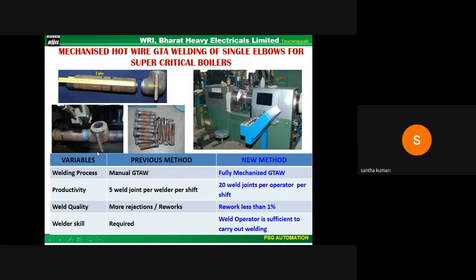Mostly, 5 weld joints used to be made per shift by a skilled welder. With the mechanized way of gas tungsten arc welding, including the hot wire addition, we were able to increase production to 20 weld joints per shift, and the reworks could be reduced to less than 1%. Even for this, an operator will be sufficient so that a skilled welder can be deployed for other welding requirements.